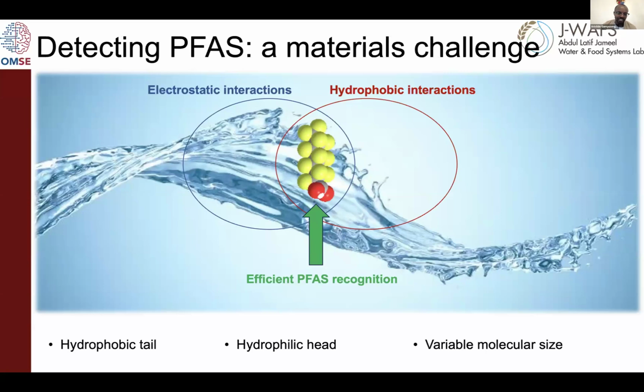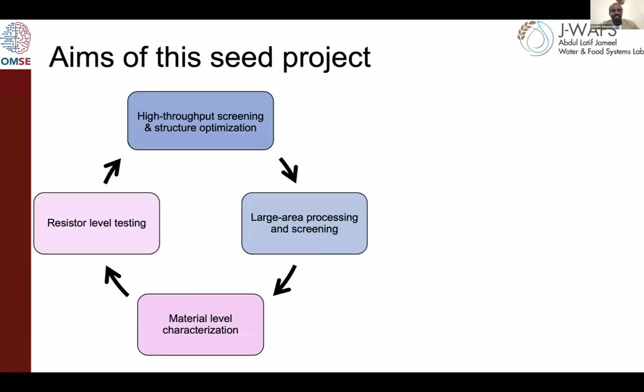And we view this as a material science challenge because, again, these are amphiphiles, so we need to figure out how to target both ends of the molecules, and in this case, for efficient detection. So this started as a seed grant actually with J-WAFS, where we set out to screen materials that could have a high affinity towards PFAS. And so we've done quite some work on this side using high throughput screening, focusing on metal organic frameworks. We have identified a few materials that we think offer some specificity and selectivity. And we've also done resistor level iterations.